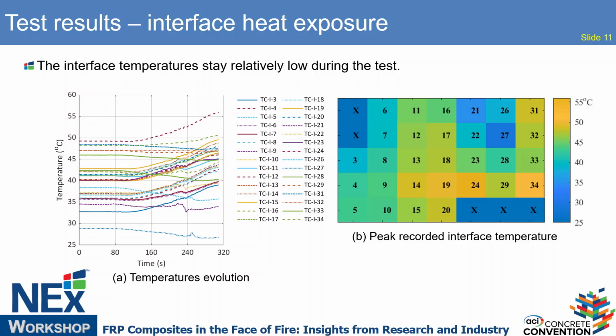For another thing, if the vehicle fire extends further, like an EV fire, an electric vehicle fire, it can last for more than 1 hour. It will be ignited again and again. So we can imagine that the interface temperature will increase significantly if the fire is extended. And although the maximum is only 55 degrees C, the thermal expansion coefficients of the polymer concrete and the concrete are relatively different. So the thermal expansion may still lead to some delamination between the polymer concrete overlay and the substrate concrete.